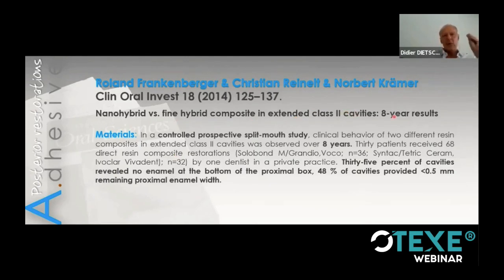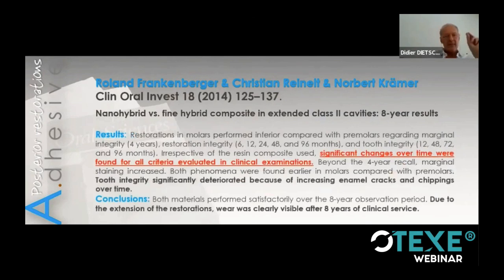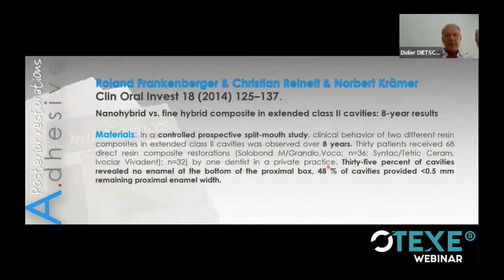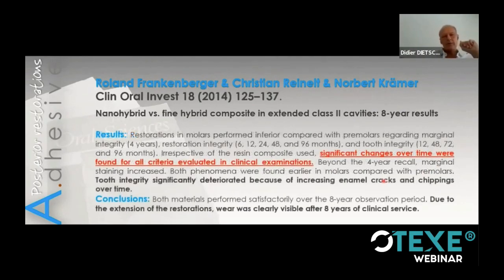We have here an 8-year result in a randomized controlled, split-mouth study, which is very, very good. And they had here really much inferior results compared to the previous situation. So there were significant changes over time for all criteria used to evaluate the restorations: cracks, chipping, basically margin deterioration. And what I wanted to show you is that here the majority of cavities, or half of the cavities, were below the CEJ or having very, very thin enamel. So clearly this is having an impact on the restoration behavior.